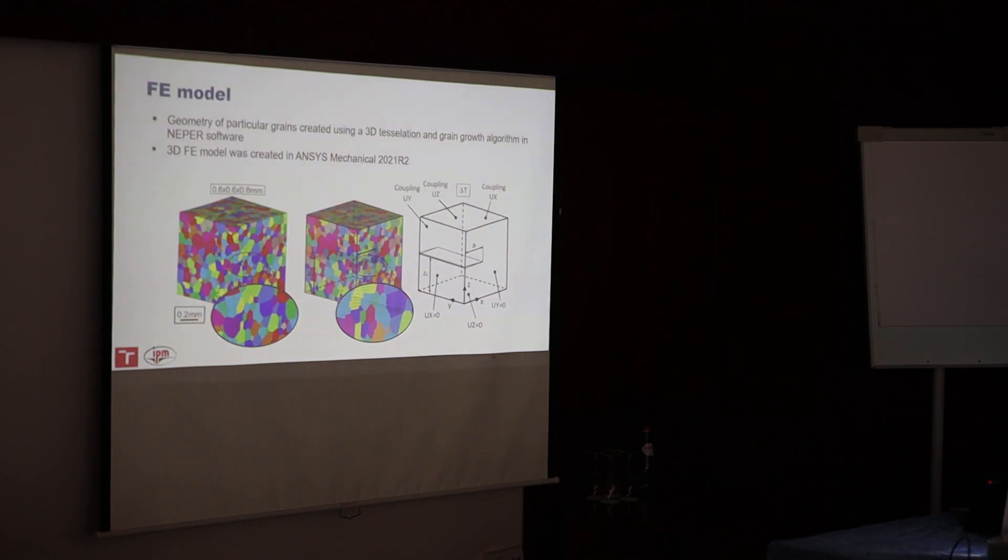We will then introduce a crack inside this microstructure and calculate the thermal stress intensity factor along the crack front, so that we can see what is the contribution of the thermally induced stresses in the microstructure to the total stress intensity factor. The higher thermal stress intensity factor will be there, the lower apparent fracture toughness we will obtain when passing the Curie temperature. This was the model of the microstructure created using 3D tessellation technique and the grain growth algorithm in Neper software.